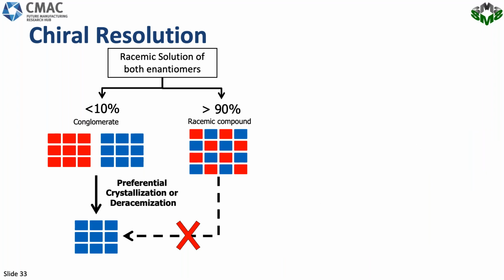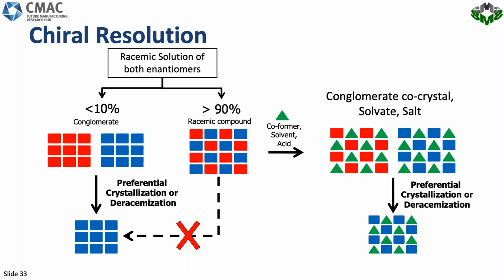So one way of getting rid of this enantiomer is to make a co-crystal, salt or solvate from it. And if you're lucky enough, then you form a conglomerate co-crystal, solvate or salt. And then you again have left-handed and right-handed crystals. And if you prevent the formation of one of them, you can crystallize an enantiomer product.